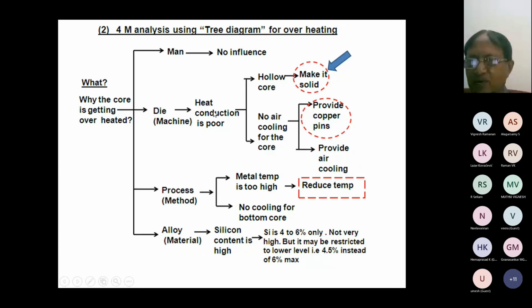Heat conduction and the hollow core. Hollow core also is a reason because it contains air and air is a bad conductor of heat. Why not we make it solid? Then no air cooling in the bottom core. Then we made a copper chill. This idea solved the problem of shrinkage, but again, it gave the problem of noise and all that. Metal temperature was too high. Then we brought it down to 720, something like that. But that makes no difference. Silicon is only 4 to 6%. There cannot be change. So boldly we wanted to make a solid core and try a big bottom core.